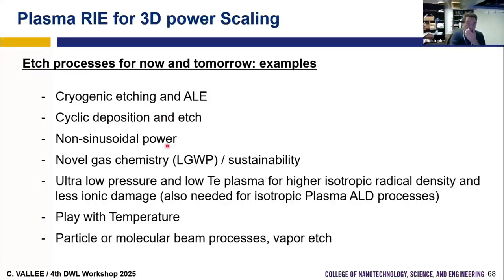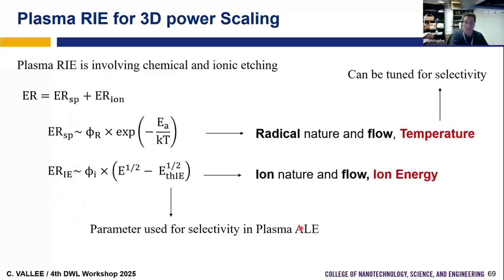We have to introduce non-sinusoidal power, so we have to change the RF bias waveform. So I told you, for example, we need to control the very narrow ion energy distribution. So maybe we have to go to RF to pulse DC, more and more pulse DC. We have to develop new gas chemistry because regarding the global warming, we have to find solution to replace some fluorocarbon gas, and it's very challenging. We have to play with temperature for sustainability, and we have to develop more isotropic etching like molecular beam or vapor etch. So first, I will talk about low temperature and cryo.